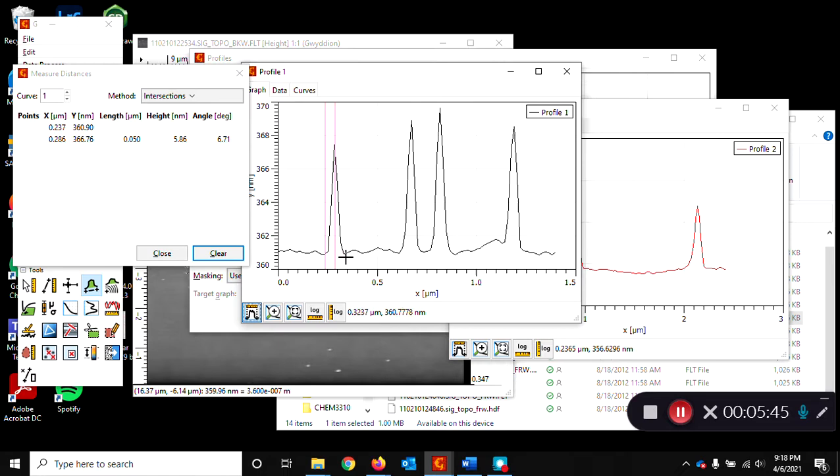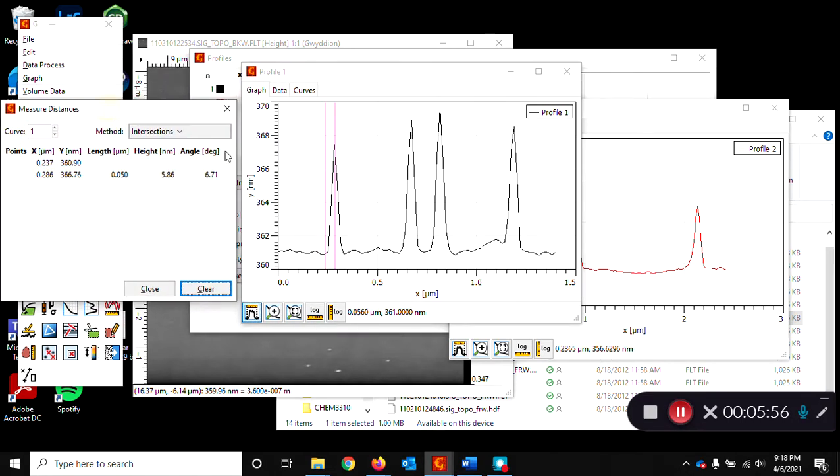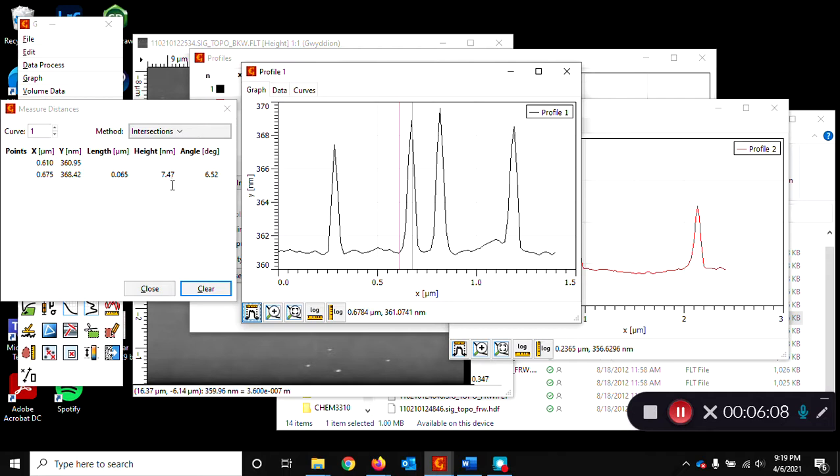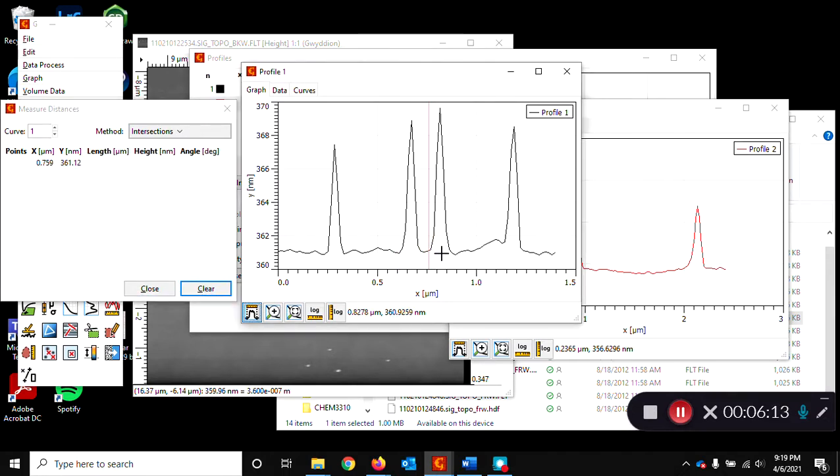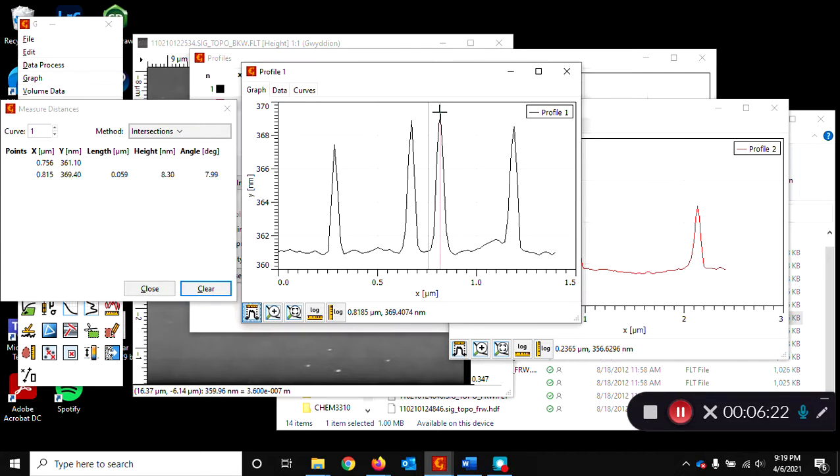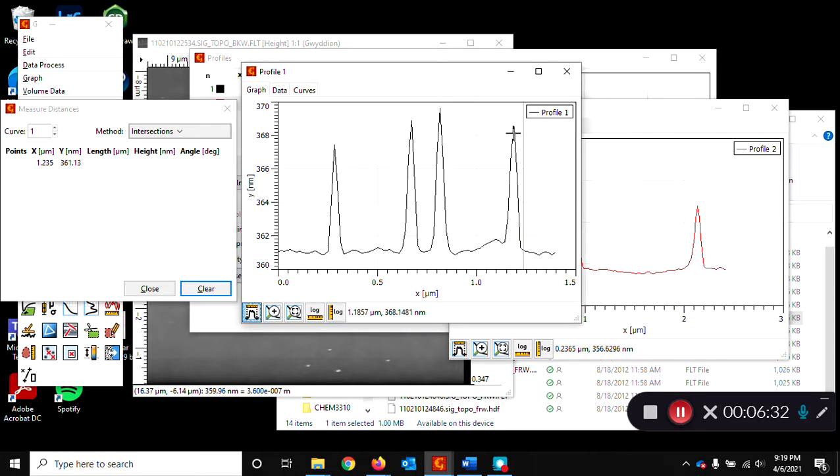What's interesting when you do these measurements, you want to write this down somewhere. There's not a good way of extracting this data or making a table of the data to save. So you write that down, this particle you measured here, and then we measured one here, 7.47 nanometers. We measured one here. Oops, I didn't quite get that. So you can see this is why the background subtraction is important because that's where your baseline is for these profile peaks. 8.3 nanometers. We got some, I guess that's the base here. 7.28 nanometers.